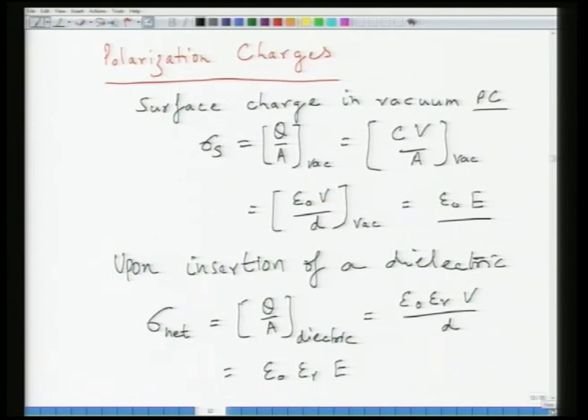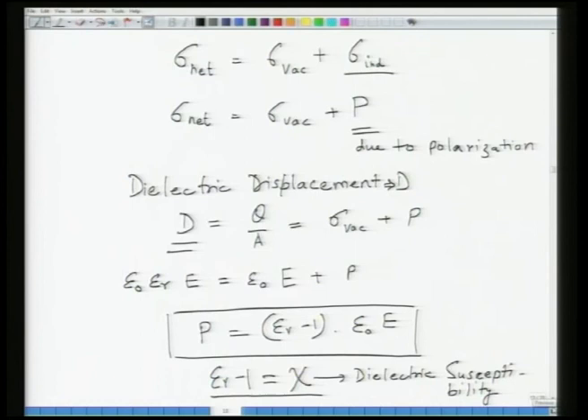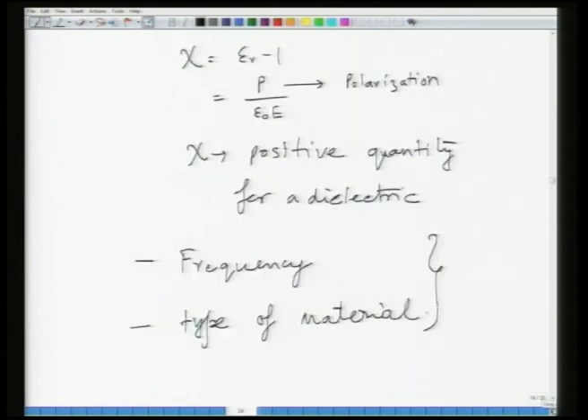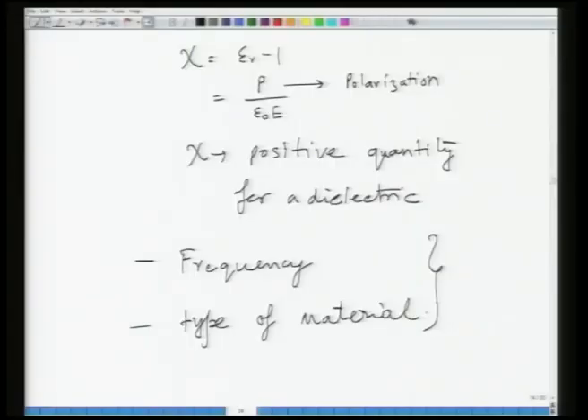And then we looked at the surface charge density mathematically, and from that we find that the net surface charge density would be the sum of the surface charges that were present without the presence of a dielectric, plus what is created because of the presence of the dielectric, and that is because of polarization. So from that we find two quantities. One is dielectric displacement, which is the surface charge density itself according to electromagnetic theory, and which is nothing but sigma vac plus P. From this we find another quantity, which is dielectric susceptibility, which is epsilon r minus 1. So basically what you have to remember is that epsilon r minus 1, or chi, the dielectric susceptibility, is a measure of the response of the system upon insertion of a dielectric, and it is the ratio of the polarized charge, or the excess charge, to the charge on the surface of a vacuum capacitor.